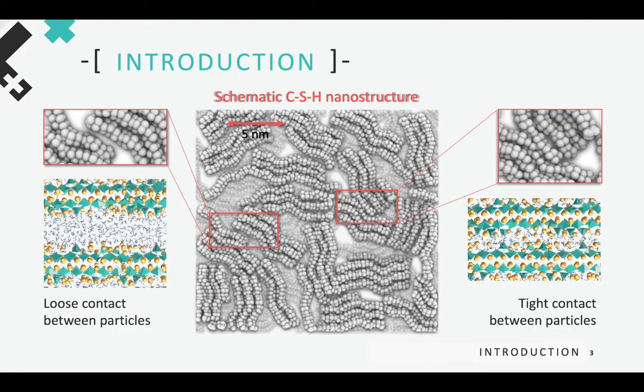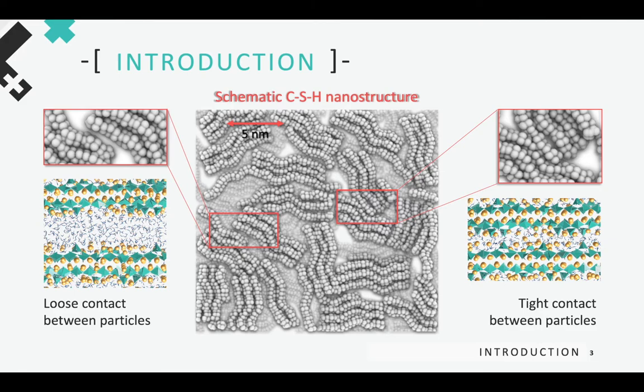As you may know, the calcium silicate hydrate or CSH gel is the main component of cement paste and responsible for most of the final properties of the material, including the mechanical performance. Nanoparticle-based simulations have shown that collective rearrangement of multiple CSH nanounits produce stress relaxation, controlling the viscous behavior, creep deformations, and thus the main modes of mechanical degradation of these materials. As can be seen in the schematic picture of the CSH gel nanostructure, the CSH nanounits are randomly oriented and aggregated, resulting in a wide variety of interfaces between nanoparticles, with tighter and looser contacts possible. The triggering of rearrangement that produces stress relaxation is then controlled by the interfacial cohesion between adjacent CSH nanounits.